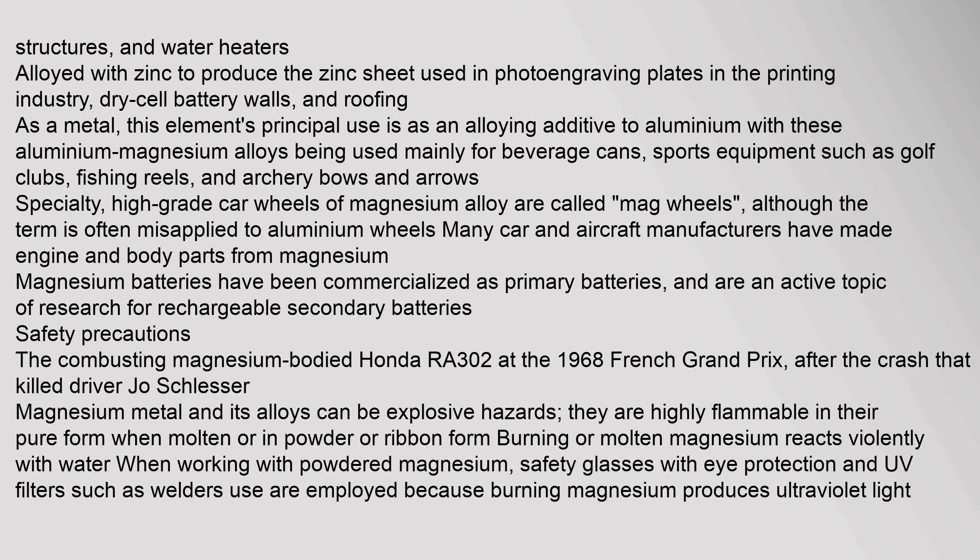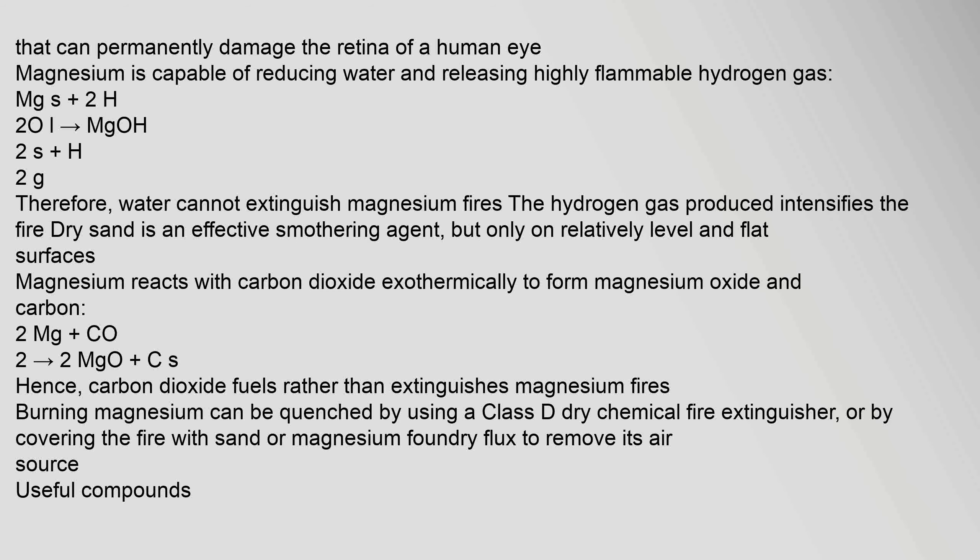Magnesium metal and its alloys can be explosive hazards; they are highly flammable in their pure form when molten or in powder or ribbon form. Burning or molten magnesium reacts violently with water. When working with powdered magnesium, safety glasses with UV filters such as welders use are employed because burning magnesium produces ultraviolet light that can permanently damage the retina of a human eye. Magnesium is capable of reducing water and releasing highly flammable hydrogen gas: Mg + 2H₂O → Mg(OH)₂ + H₂. Therefore, water cannot extinguish magnesium fires.